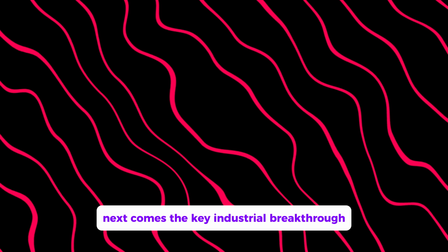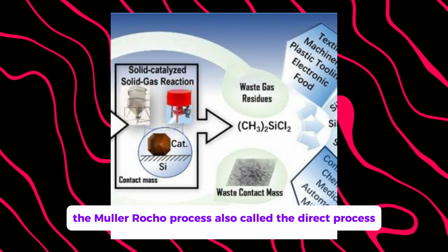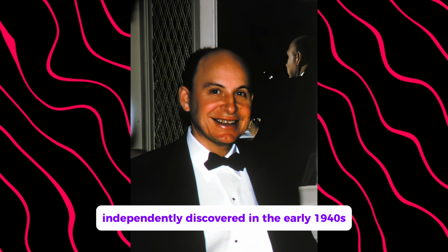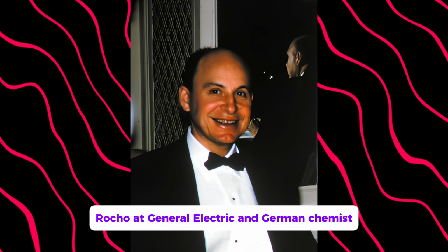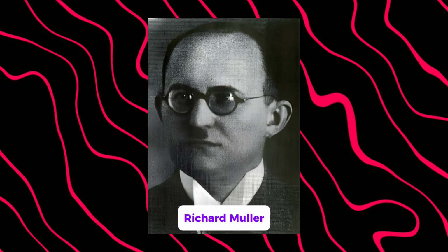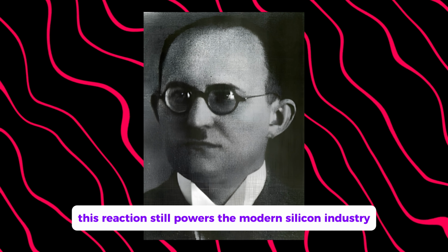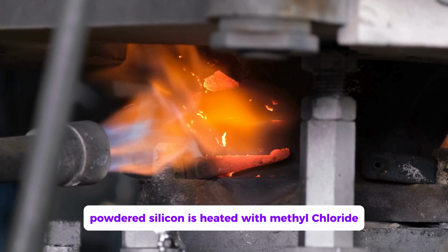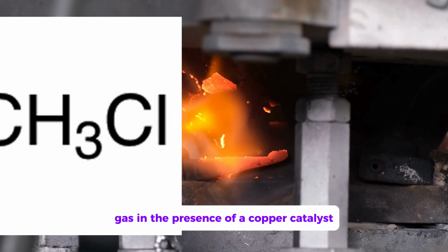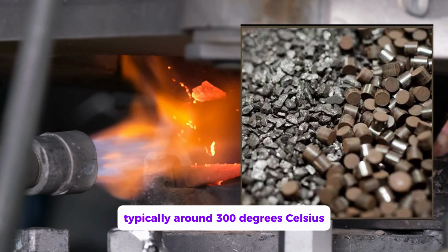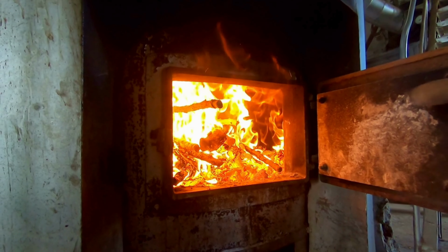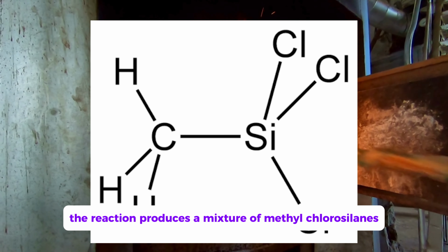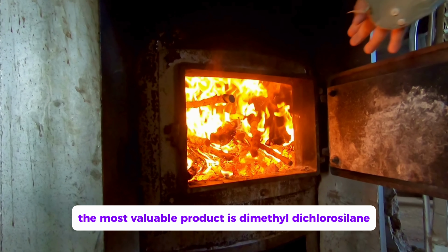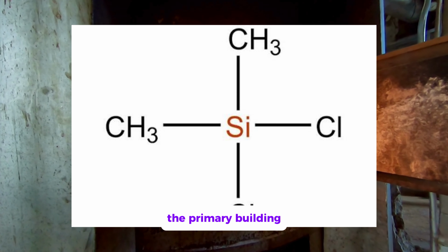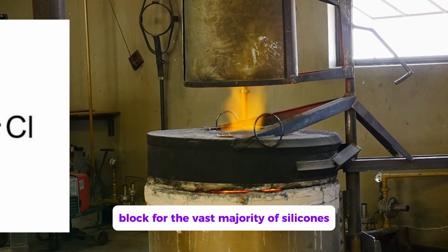Next comes the key industrial breakthrough, the Müller-Rochow process, also called the direct process. Independently discovered in the early 1940s by American chemist Eugene Rochow at General Electric and German chemist Richard Müller, this reaction still powers the modern silicone industry. Powdered silicon is heated with methyl chloride gas in the presence of a copper catalyst, typically around 300 degrees Celsius. The reaction produces a mixture of methylchlorosilanes. The most valuable product is dimethyldichlorosilane, the primary building block for the vast majority of silicones.